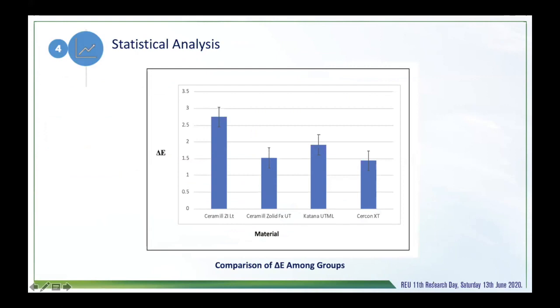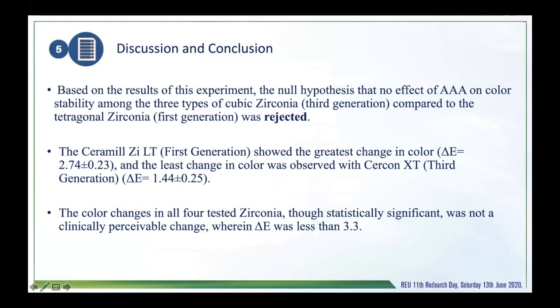A one-way ANOVA test shows there is a statistically significant difference among the groups, where the Ceramill Zi LT showed the greatest change in color, followed by Katana, then the Ceramill Zolid, and the least change in color was Cercon XT. So, based on the result of this study, the null hypothesis was rejected. The color changes in all 4 tested zirconia were statistically different, but there was no clinically perceivable change, as the delta E was less than 3.3.